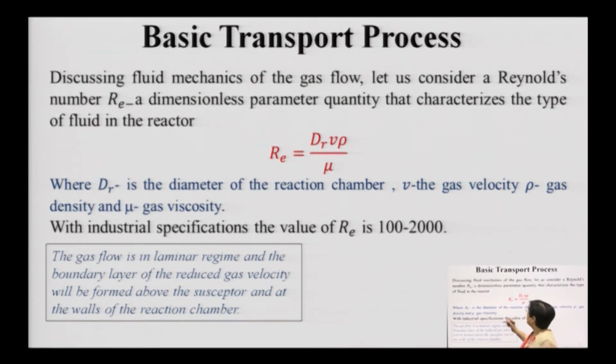Now, please understand, the gas is allowed to flow onto the material, and when you have the wafers lined up over here, gas is introduced from here. This gas is going to flow over the wafers. Please remember, here you have a certain velocity v, and when it approaches the wafer, this velocity is going to degrade slightly, and a stagnant layer gets formed, because of which the adsorption or the layer formation is going to happen.